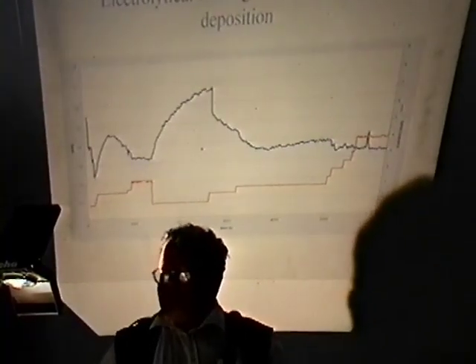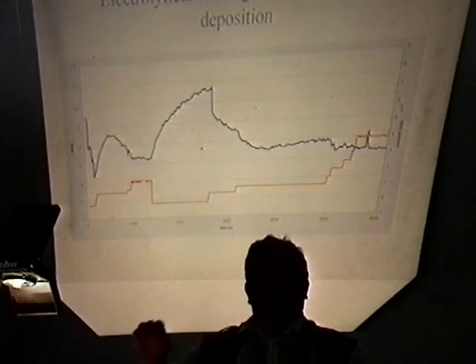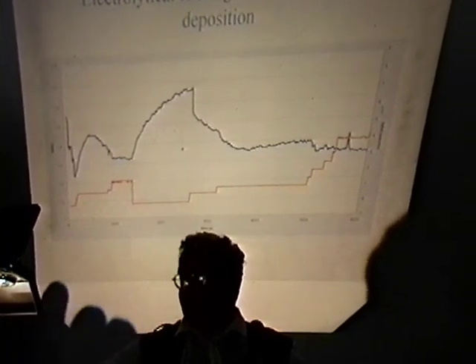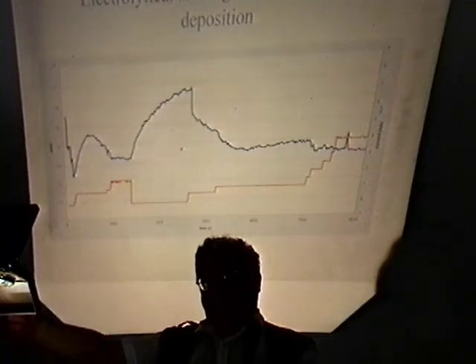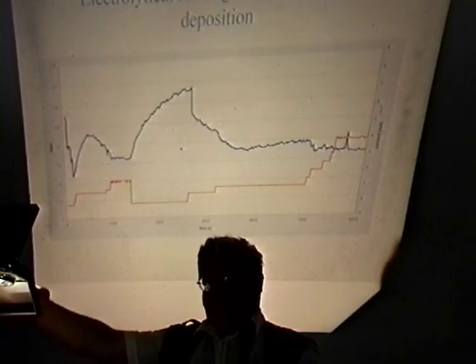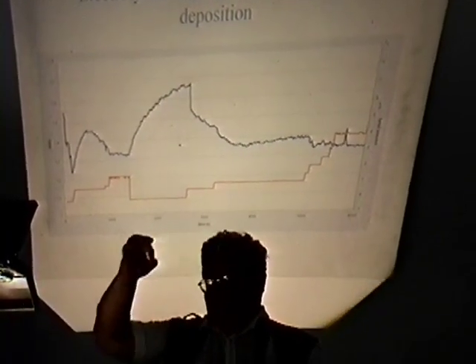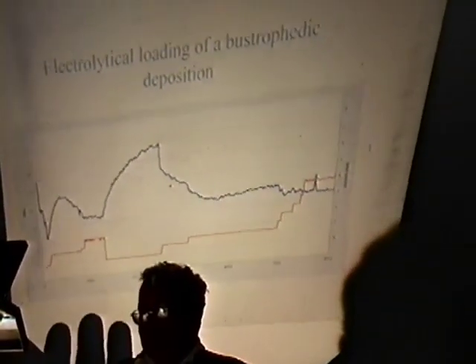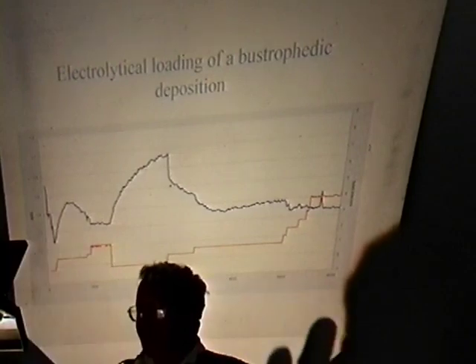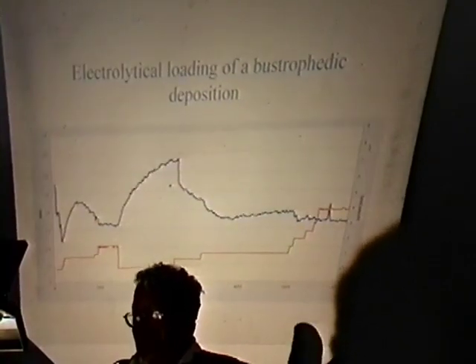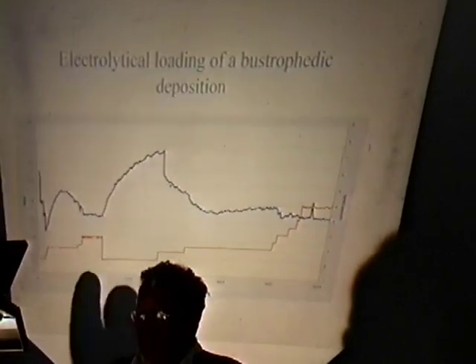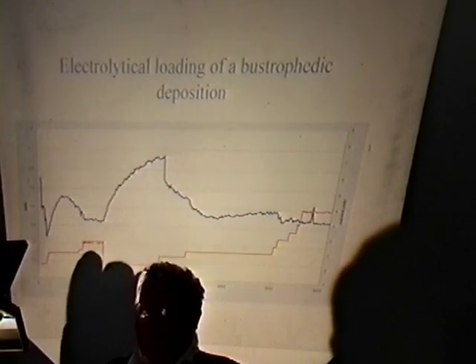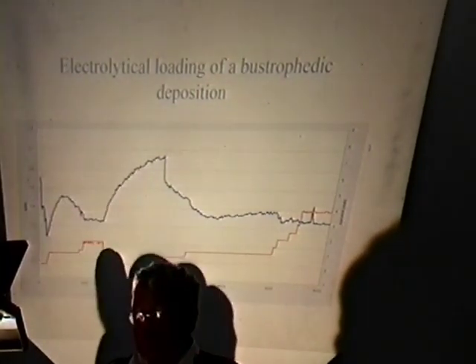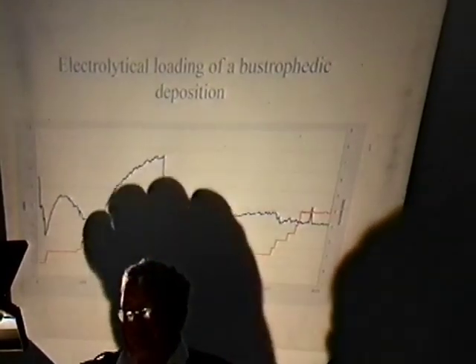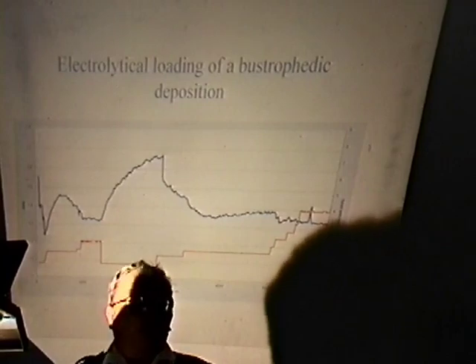Now, let's take the deposition. Same regime. We don't apply an external potential because we use just the ohmic fall of the cell potential along the current. So we don't apply an extra potential. This ohmic fall is enough to produce this change. You can see that now when we apply the current, R over R naught decreases. When we remove the current, it increases. And vice versa. What does that mean?